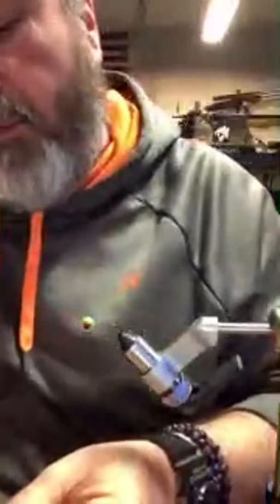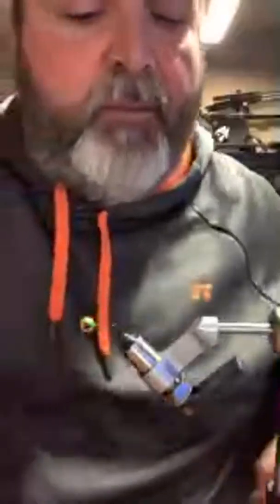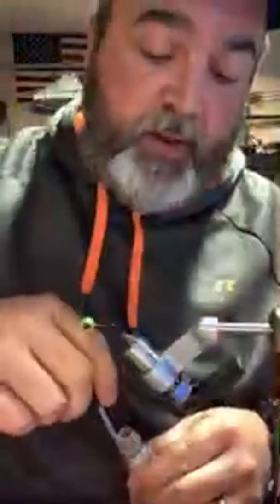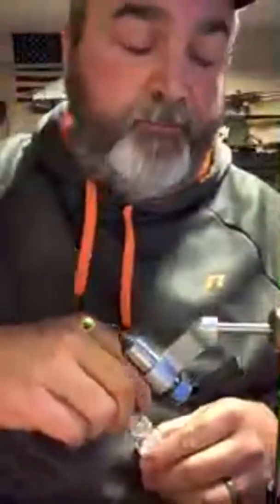Yes, I powder coat all my jig heads. I powder coat them all, and then I bake them all in the oven at 350 degrees for 20 minutes. I don't usually put a clear coat on it or a hardener. I prefer to bake them. But yeah, all the jig heads I paint, I powder coat every one of them. And I powder coat them and paint them myself. I buy them unpainted and do it myself. That way I know for sure what I got. I know the paint's durable. I know it's going to last. And it keeps me from buying.